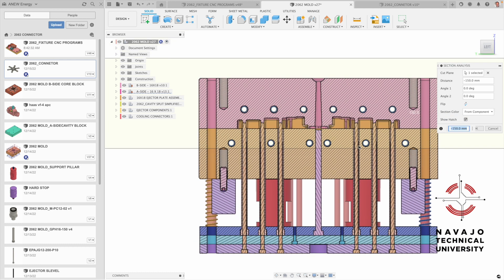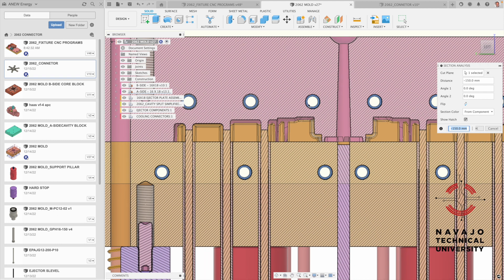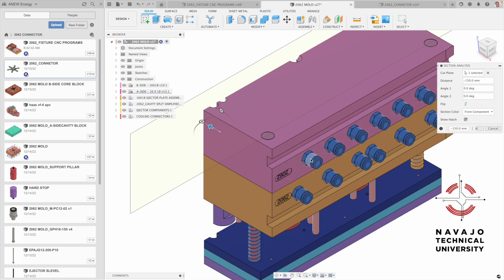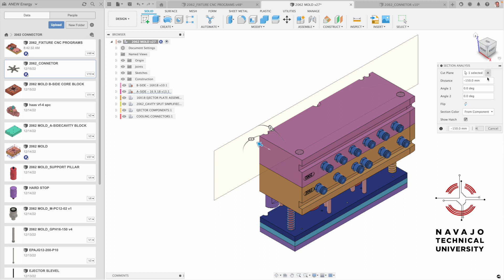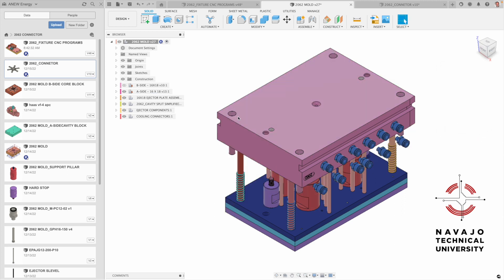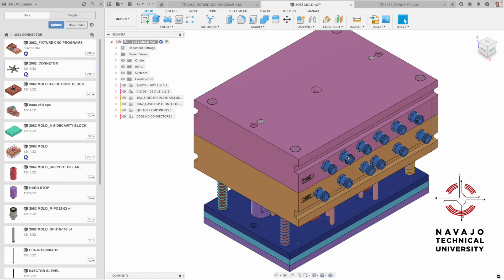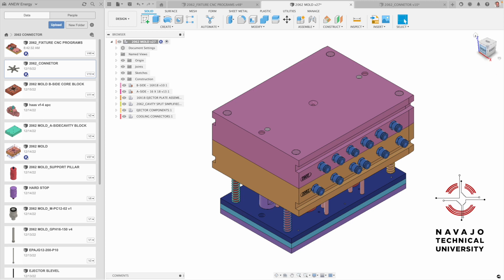These are water lines that cool the part — we want as much cooling as possible. Water is routed in and out through a big manifold that processes a lot of water at one time. That's the mold, which slips into an assembly on the molding machine so you can drop it in and out quickly. The A-side and B-side water temperatures can run differently — nylon processes at about 525 degrees Fahrenheit, so we want it hot briefly then cooled down.